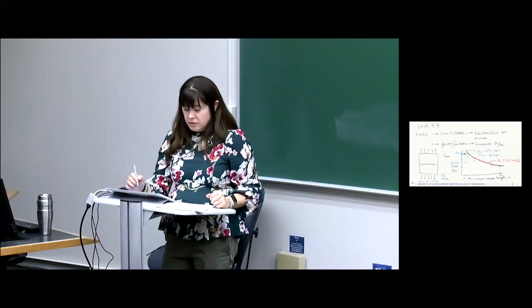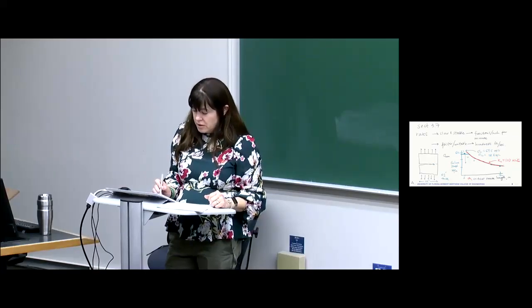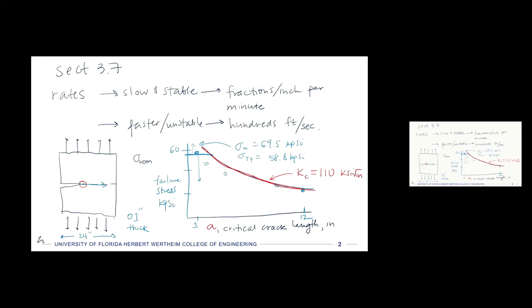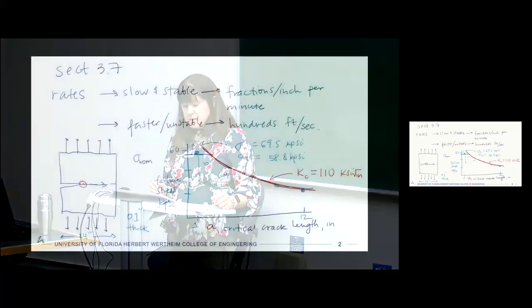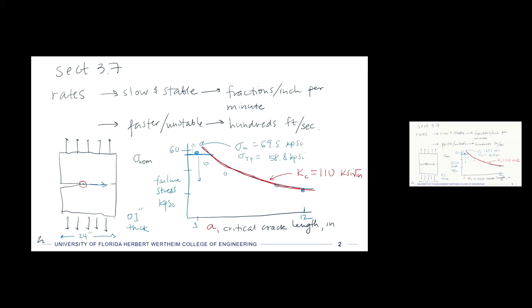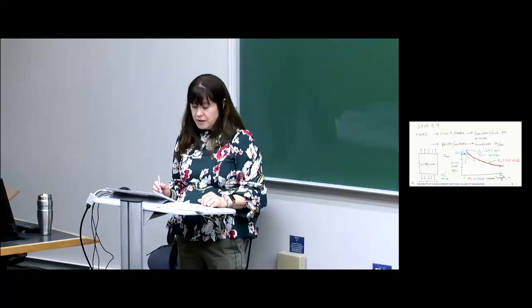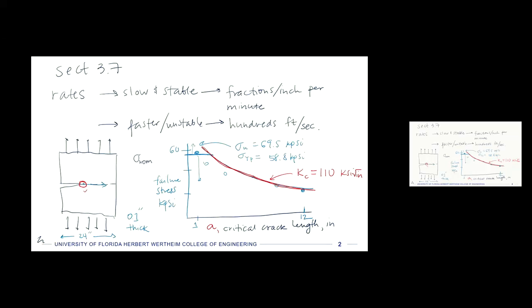I said that we were going to talk today about linear elastic fracture mechanics, right? But you can make an argument that at the crack tip right there, there's no possible way we could have elastic deformation, because we're literally taking the material and breaking a bunch of bonds and warping it, and so there must be some plastic deformation there. And so I want to say your intuition is not wrong, but in linear elastic fracture mechanics, what we do is we compare the zone of that plastic deformation with the larger idea of the stress affecting that crack. Okay? So as long as this little plastic zone remains small compared to the length of the crack, a, then we can assume that most of this material, even near the failure area, is in a linear elastic regime. So that's why we call this linear elastic fracture mechanics.